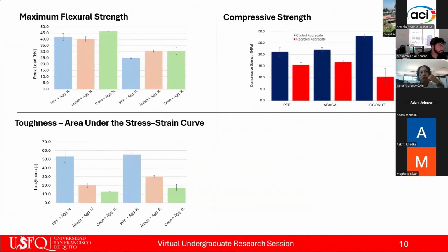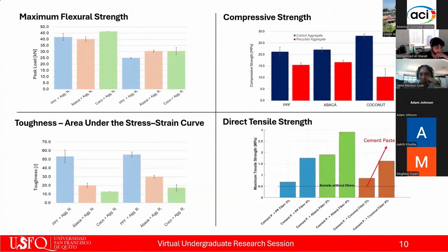Compression using recycled aggregates lowered the strength by roughly 1/3 compared to normal aggregates. Even so, coconut and abaca fibers added a slight recovery, likely due to internal curing from water retention. Fiber type did not change compressive strength directly, but it did influence curing behavior. In direct tension, every fiber reinforced mix surpassed the baseline cement paste. Abaca fibers stood out, reaching up to 2.12 megapascals, followed by coconut and then polypropylene, which improved notably at higher dosage. Here again, synthetic fibers allowed larger deformation, indicating greater energy absorption capacity.